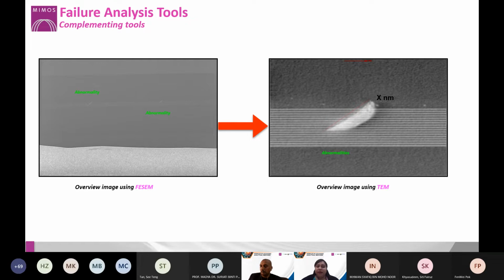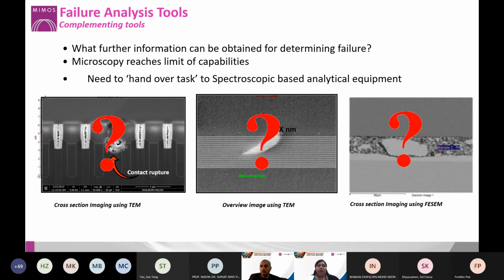So as I mentioned just now, we can't get a clear image. As you can see, there is an abnormality in the FIB SEM image, but you can see the overview by using TEM, and then we magnify it further. You can go up to very high magnification and get a very clear image of your abnormalities, and we can also measure it. Some customers require knowing what element is present at this particular abnormality, whether it's a copper migration on your sample or something else. So we do the EDS mapping. I'll explain further. Okay, so what further information can we obtain for determining the failure?